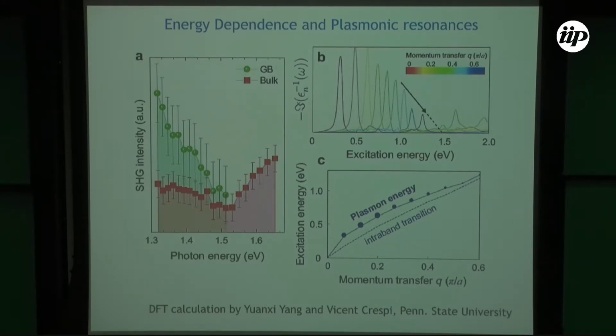For MoS2, the band gap is about 1.5 eV. So we don't observe any second harmonic emission from the grain boundaries for energies that are above this band gap. We only observe it below the band gap, and it decreases at a much faster rate than the bulk emission.